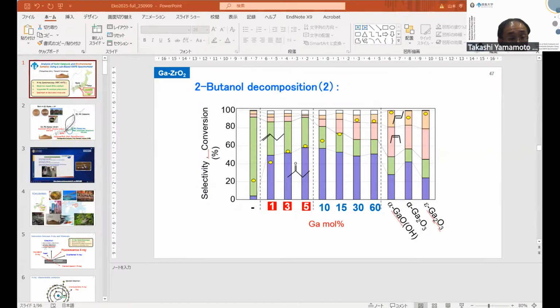The methyl ethyl ketone, the dehydrogenated product, was obtained with high selectivity and yield like this. The selectivity did not change up to 5 mol percent, but at more than 10 mol percent, the selectivity changes and the amount of internal olefins increases like this. This is similar to that over the gallium oxide as it is.